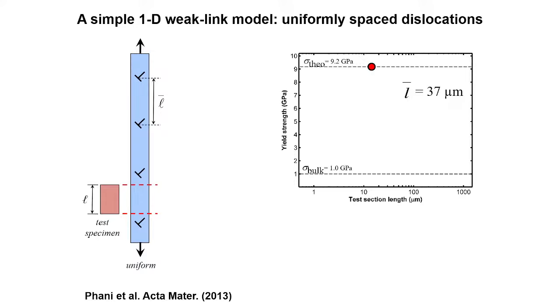And then depending, if you do a Monte Carlo simulation, right, of uniformly spaced dislocations, and you do lots of simulations, right? Sorry, before you do the Monte Carlo simulations, you could now do a weighted average of this one and this one, where this is the bulk strength multiplied by this ratio of L over L bar, and when L is large compared to L bar, which means the specimen length is large compared to L bar, then this term dominates, sigma bulk dominates, and you would get things that behave like the bulk. In the other case, this one dominates and you get behavior that looks like this. And then this equation is simply this one, right?